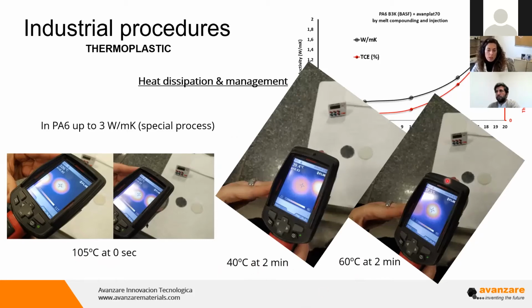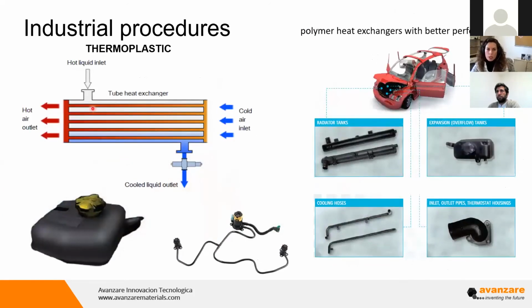This is because the thermal conductivity of polyamide is near 0.2 watts per meter Kelvin, where we are adding these graphene materials. And in some cases, depending on the process and the kind of polyamide, we are going up to 3 watts per meter Kelvin. So what we can do with these kind of materials is prepare polymer heat exchangers, as for example what you can see here: these pipes, cooling hoses, radiator tanks. The heat that we exchange with the fluid is more, and in a quicker way.